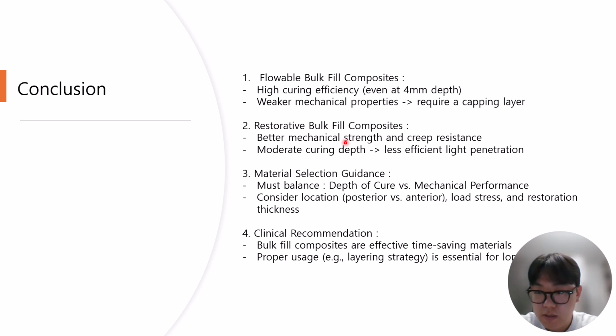restorations. Second, restorative bulk-fill composites had much better strength and creep resistance, but their curing depth was more limited, which means light doesn't penetrate as deeply. So, for thick restorations, we need to be cautious about the depth of cure.